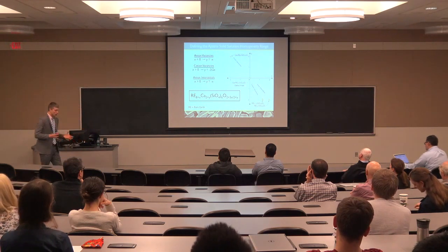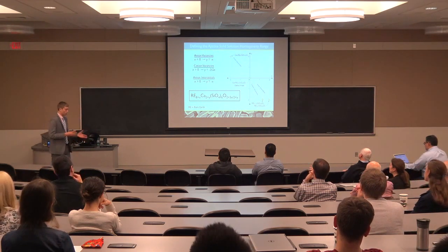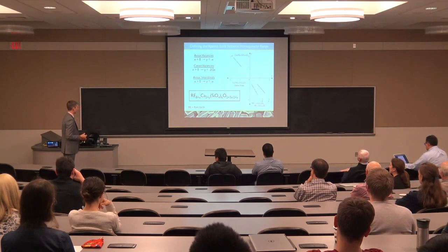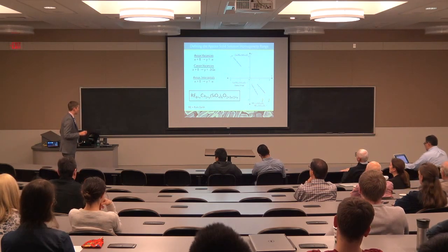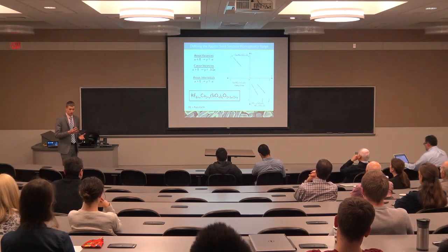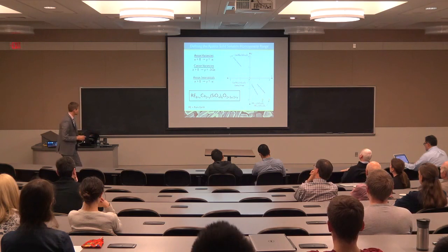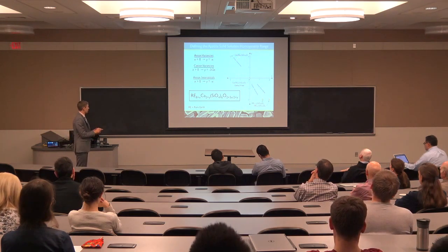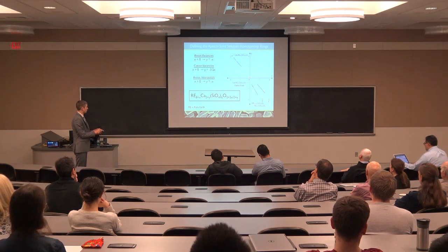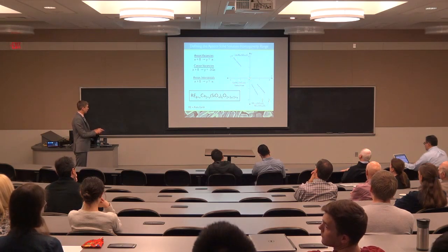So we know that apatite is important to the process. The crystallization of apatite is ultimately what we'd like to understand. So we can start by trying to map out where apatite is stable, what range of compositions. When we look at the crystal structure and the allowable substitutions we can do in the crystal structure, we find that we can have a range of compositions that extend over this range, where this is the nominal initial composition.